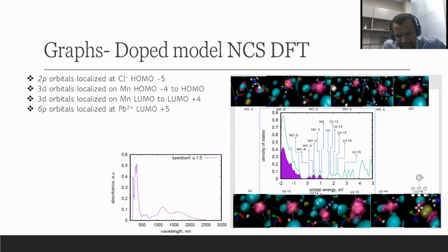I know that the energy difference that we have from HOMO to LUMO is even less than 1 electron volt, which would correspond to a peak, I would say, above at least 1000, close to maybe 1500. So I wanted to see the whole thing, but it seems like we have a higher peak around, I don't know, 200 to 400 nanometer. I mean, I still see that peak around 1500, but I don't think this one would be much relevant compared to the other ones, which look like having higher intensity or higher absorbance.